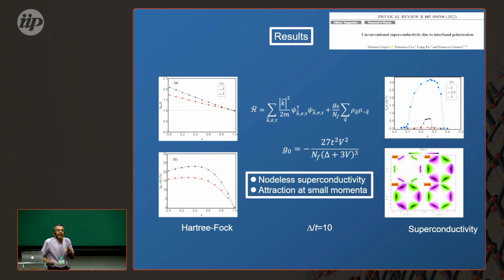Okay, but that's the point. These guys were very smart, and they already made the jump from pairing in real space to the formation of a superconductor. And now we work in reciprocal space, and we show that by solving the gap equation, what we did is BCS.